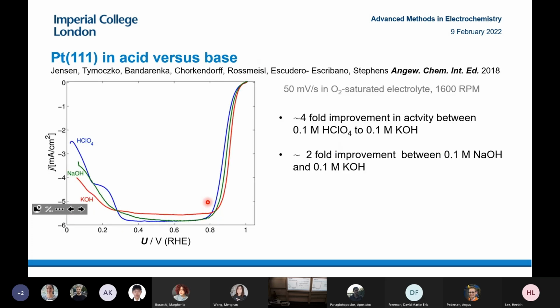We then went on to try measuring platinum-111 in acid versus base. And one thing we found actually wasn't very well reported in the literature, surprisingly, even though this is a really well-known model surface. So even on platinum-111, there's quite a big difference between acid and alkaline. If you look, let's say, in potassium hydroxide, you see a fourfold improvement in oxygen reduction activity. And sodium hydroxide is somewhere in between. So changing the cation has just as much of an effect as changing the pH from pH 1 to pH 13, which is kind of surprising to me.